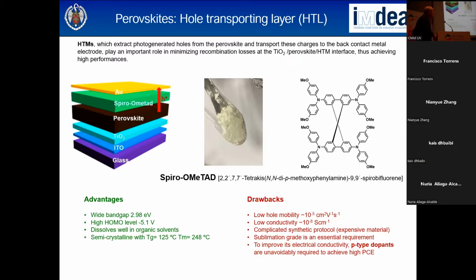Which ones? Low hole mobility. It is an organic compound, and organic compounds are not characterized by moving charge very efficiently. So the mobility is 10 to the minus 5. And also, because of the low mobility, low conductivity. In addition, because of the chemical structure, it has a complicated synthetic protocol, and because of that, it is quite an expensive material.